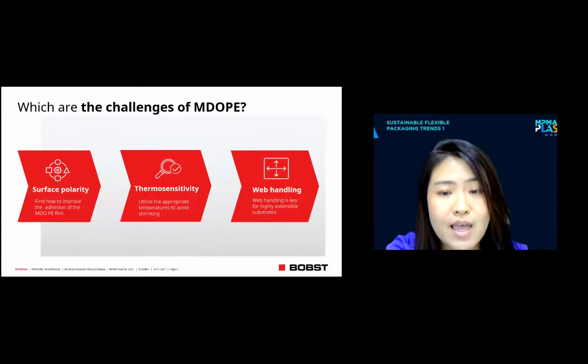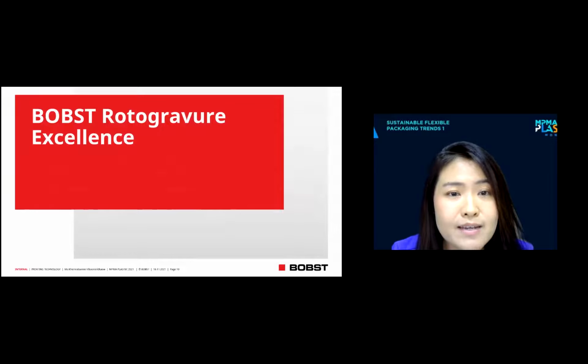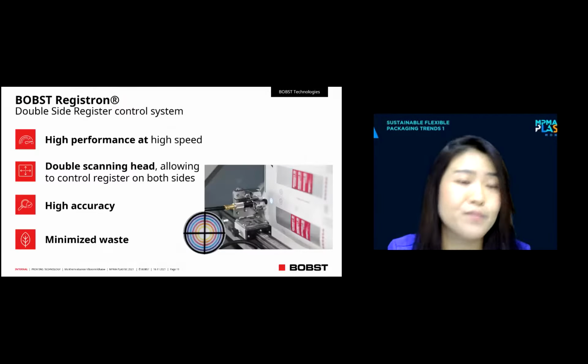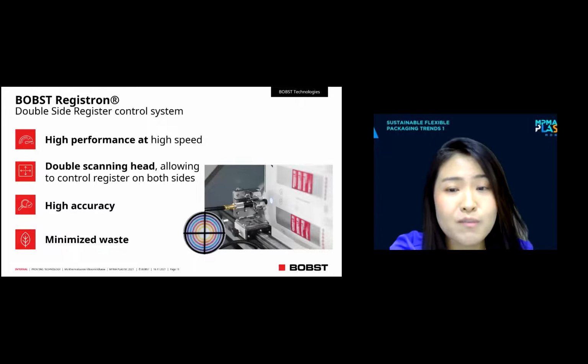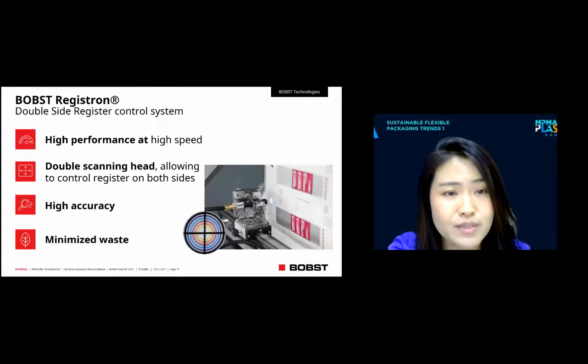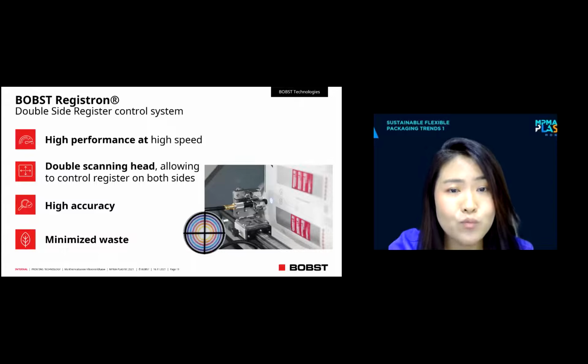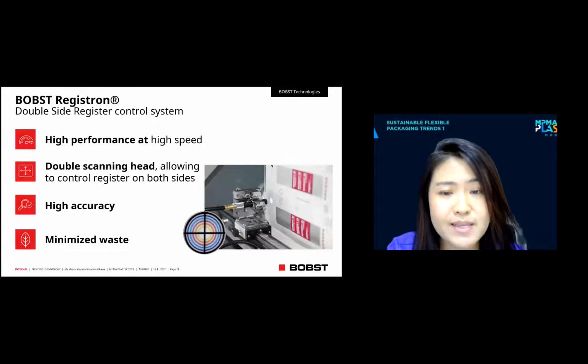The MDOPE has a tendency to stretch, especially upon the combined application of heat and tension in the dryer. For instance, on the printing side, we also make sure that our MDOPE film will not stretch and also not shrink during the processing. On our rotogravure, we ensure that the substrate put on the machine can be handled with the best print performance on the MDOPE film. Thanks to our Bobst Registron, we have a high-performance, high-speed double-side registration control system. And the accuracy is very high: less than 30 micron for the length and the side registration. And our double scanning head can also read poor contrast colors, even through the coating, to ensure that we get precise print quality and minimize waste.